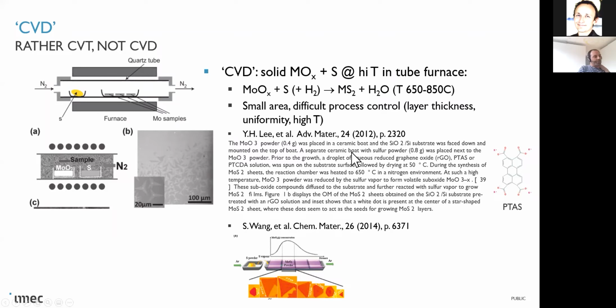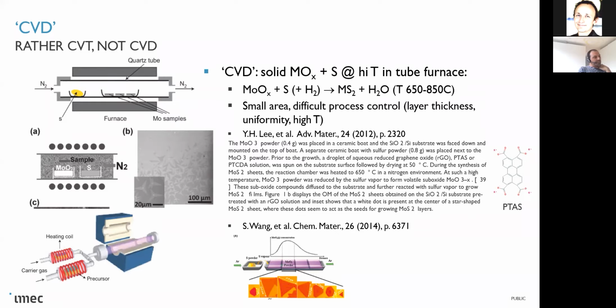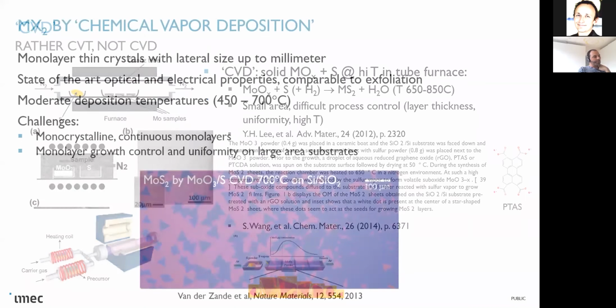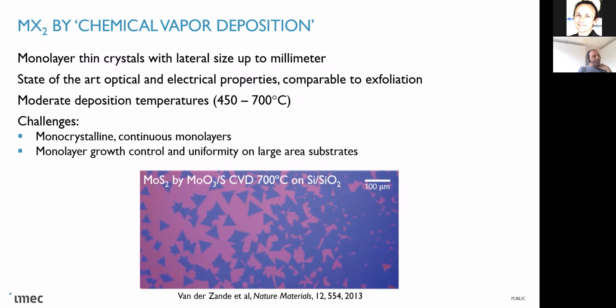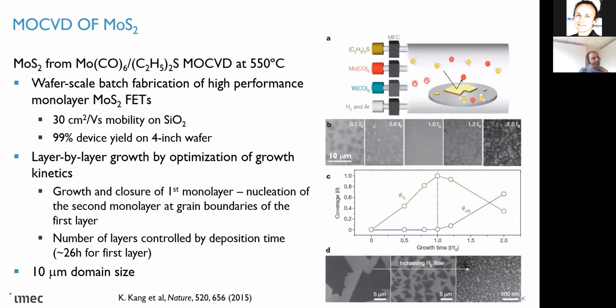Basically, this is something we disregard because we don't believe that this can be easily tuned towards a stable 300 millimeter process. Nevertheless, I think most of the high-level results that are achieved today in the labs are mainly delivered through this method, and it's also very versatile, so you can very easily make very different 2D materials through this method. This is, I think, a reference paper for everybody who is growing these 2D materials, as it was kind of a breakthrough, as they demonstrate 30 centimeter square per volt per second mobility directly grown on silicon oxide for molybdenum disulfide with a remarkably high yield.